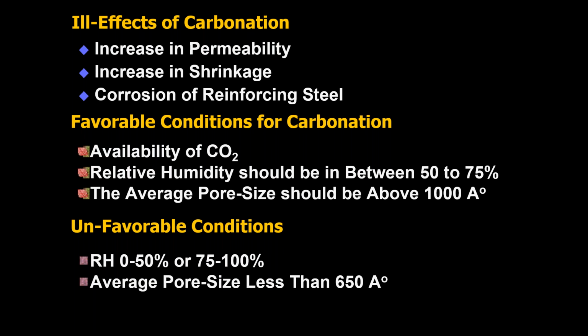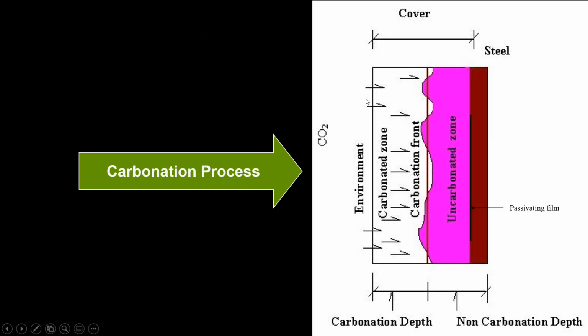What are the unfavorable conditions for carbonation to take place? When the relative humidity is between 0 and 50, it will not take place. And also when the relative humidity is between 75 and 100, because pores will get saturated, the carbon dioxide cannot enter into them. And also when the pore size is less than 650 angstrom units, then also carbonation will not take place. Yeah. So this is the picture.